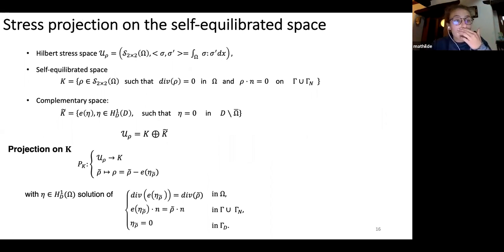And so we're not using a gradient descent anymore. We will use a projected gradient descent because it happens that the self-equilibrated space is in direct sum with a complementary space that is easy. And the direct sum of both actually makes the total stress space. So if we optimize a stress field in this domain and we project it onto this space, we will have a correct result.